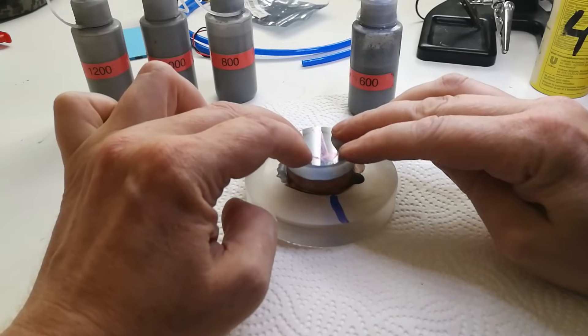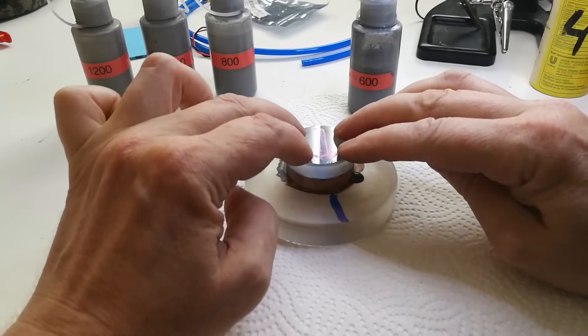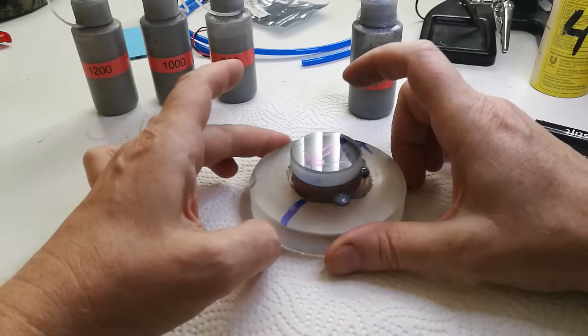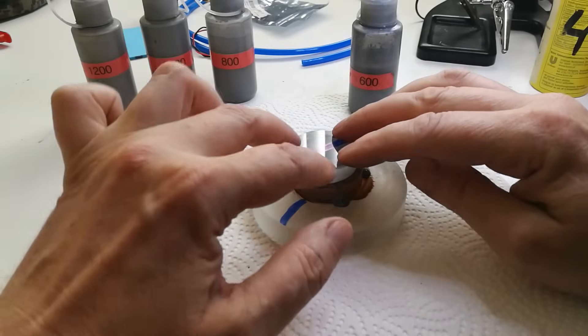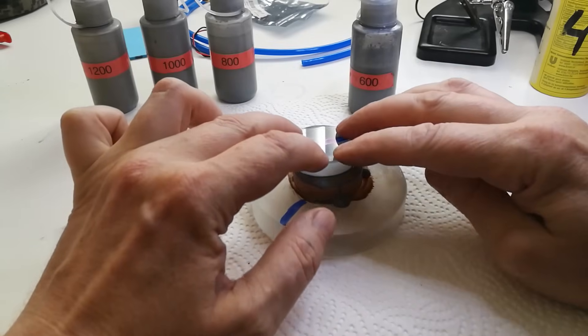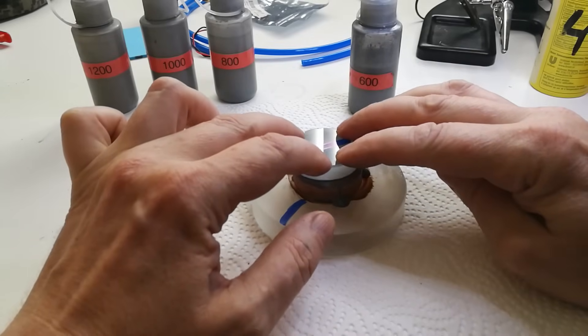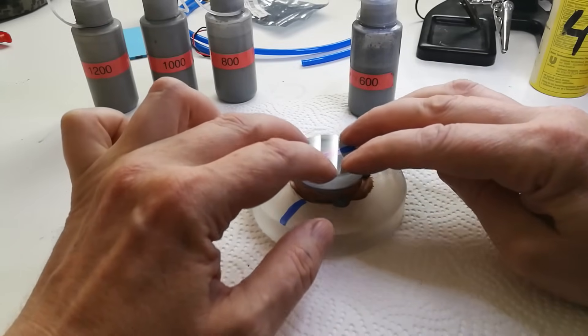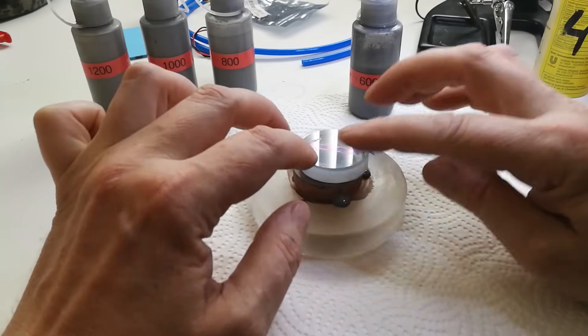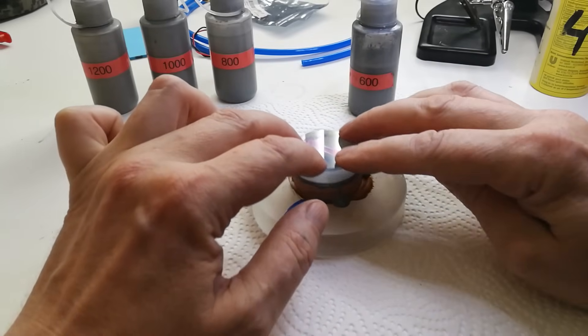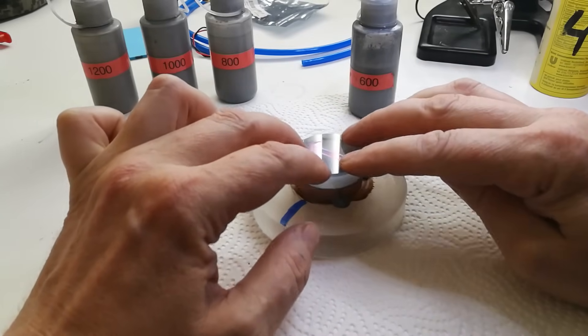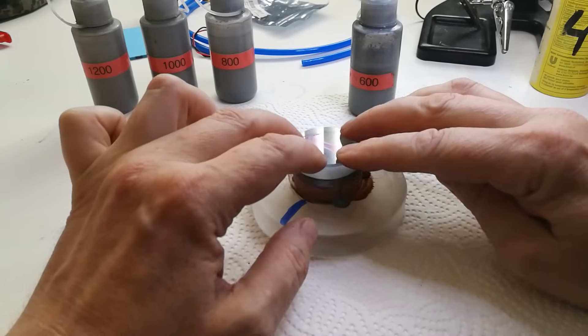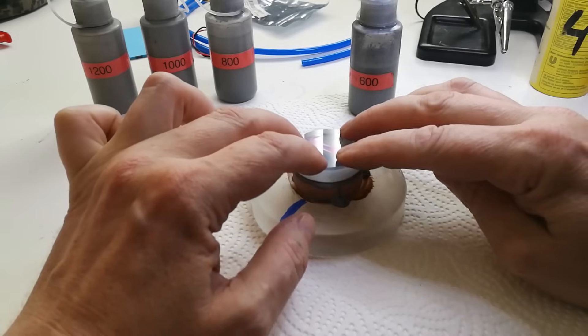We start off by using a relatively large silicon carbide grain, for example 220 or 400 mesh for a longer period of time, let's say 20 to 25 minutes for this size of blank.